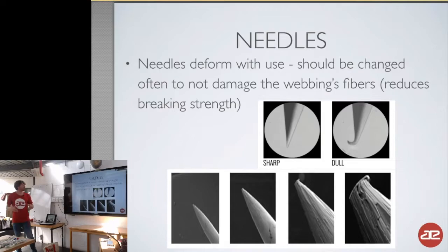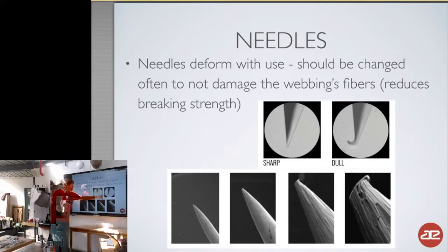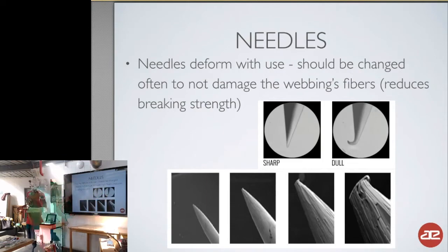What's really important for needles when you sew webbings is that if you use a needle in a machine and you put it through the webbing again and again, like in this pattern, about 200 stitches, every needle has wear. And when a needle wears off, the tip can become dull. If a dull tip goes through the webbing and goes back up again, it will destroy the fibers. You won't necessarily see this, but of course this will decrease the strength of the webbing.